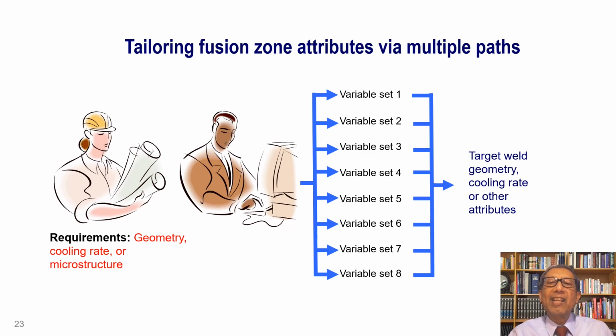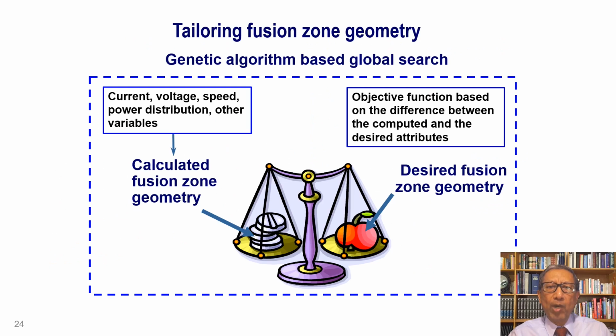So let's take an example. In our forward model, we specify current, voltage, scanning speed, and other variables such as thermophysical properties to calculate fusion zone geometry. We can repeat this exercise many times by providing many different combinations of variables and check what kind of fusion zone geometry we are getting, whether we can get a match between what we want and what we calculate. If there is a mismatch, we can go back and redo this.